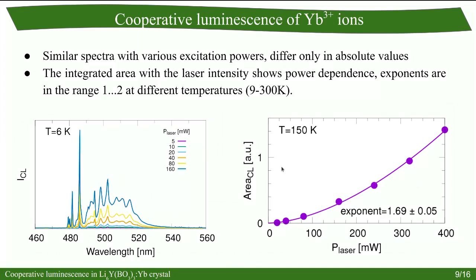The laser excitation intensity dependence: we recognize that the emission spectra seems to be the same with the intensity of the laser, just the absolute value of the spectra is changing. And if we check one temperature and we plot the integrated area versus the laser intensity, then we can see that we have a power function, here with an exponent of 1.7.